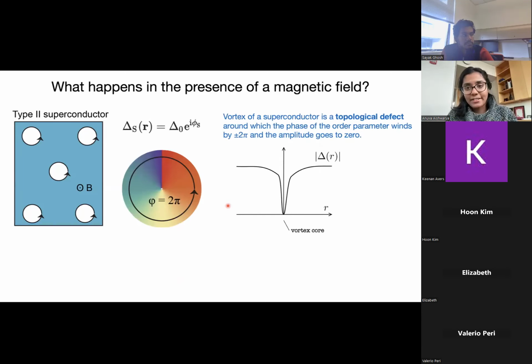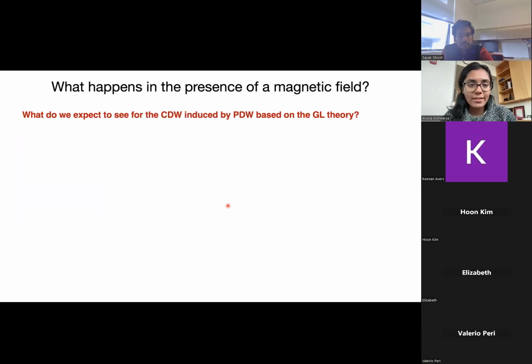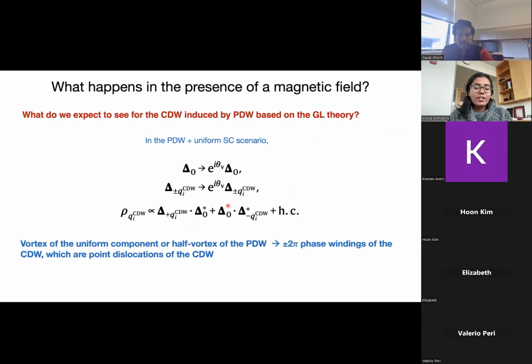And then what do we expect if we have the CDW that is induced by a PDW based on our Ginzburg-Landau theory? So in that scenario, we would expect magnetic field to punch vortices in both the uniform component, which is delta naught, and the PDW component, which is delta Q. And that means we should have vortices in the CDW. And these vortices of the CDW are basically dislocations in the CDW where the phase of the CDW winds by 2 pi. So this is the expectation. And the question is, can we verify this?